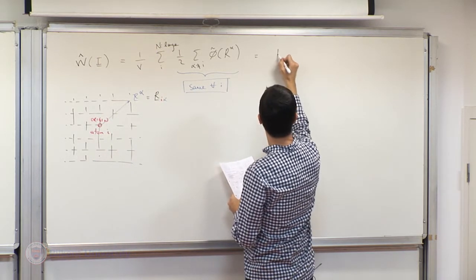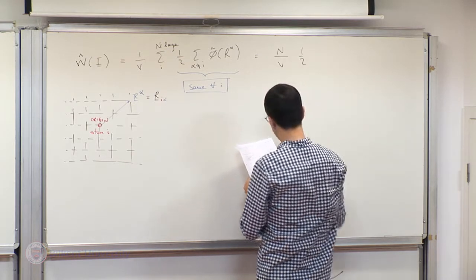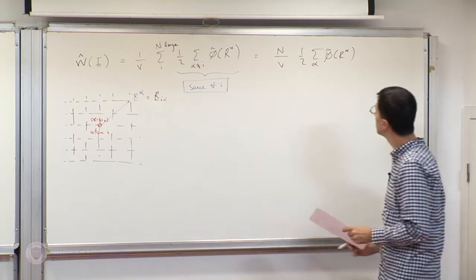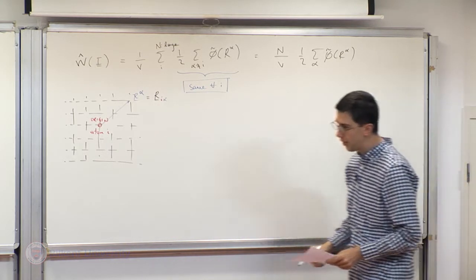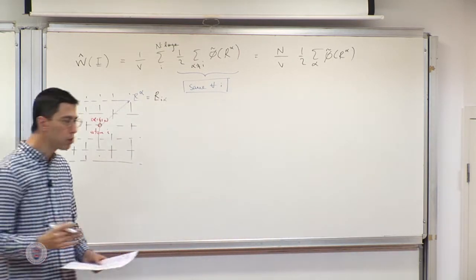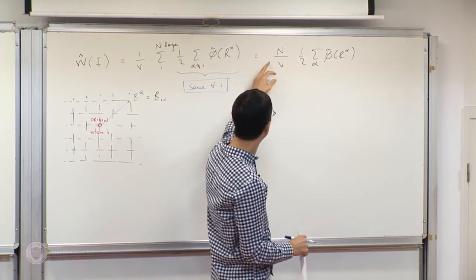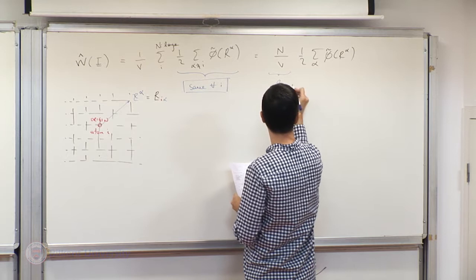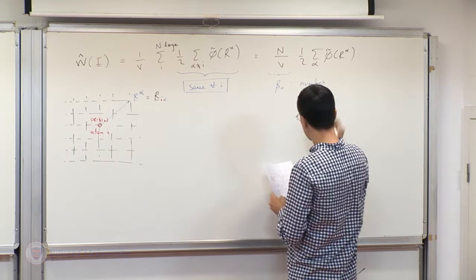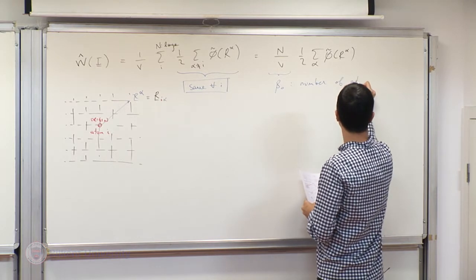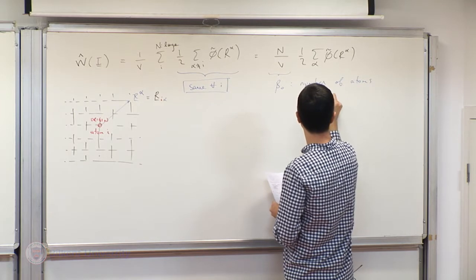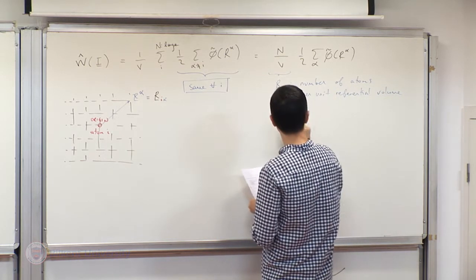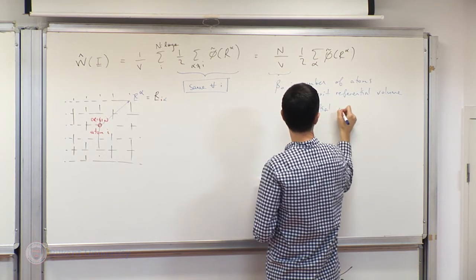This is equal to n/V times one-half times the sum over alpha of phi-tilde(r_alpha). There now appears a term very similar to mass over volume — which would be density — except instead of mass I have a number. Let's call it the referential atomic density: the number of atoms per unit referential volume.